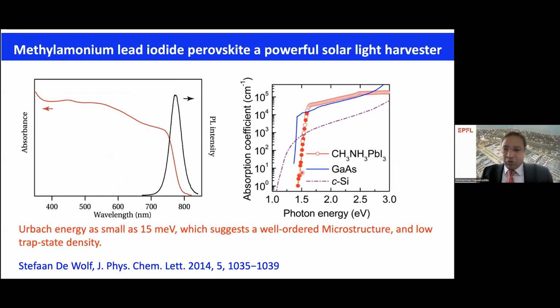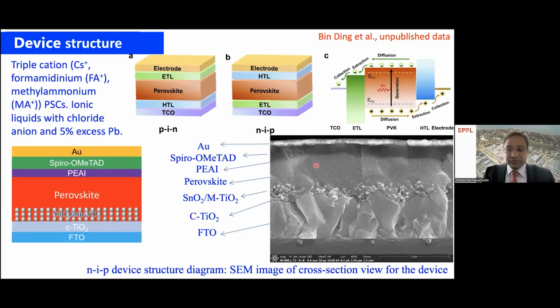The other interesting property of these materials compared to silicon is this: the purple line is the silicon solar absorption, which has a very sluggish onset. Compared to gallium arsenide, which has a very sharp onset, the perovskite materials have a similar sharp onset, showing that these materials have a well-ordered structure with low trap state densities. So these are the interesting properties of these materials.